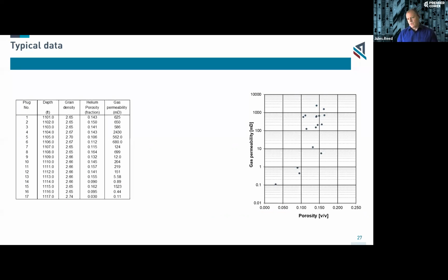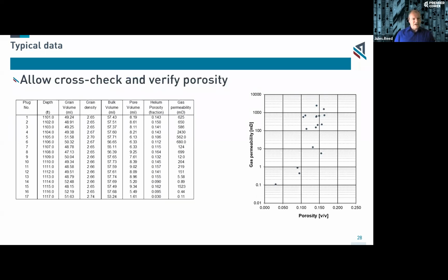And we can see that's quite a spread of permeability for quite a small spread of porosity. A little, around about 15% porosity spread, but over 4 magnitudes of change in permeability. So is there any better way of understanding those data? Well, we could get additional data because the lab has these data.